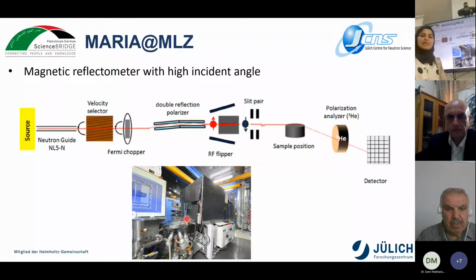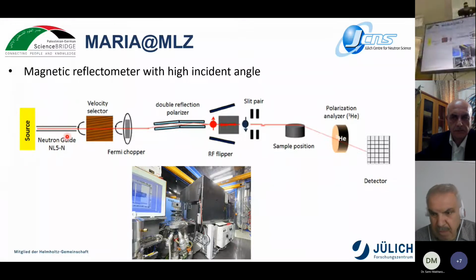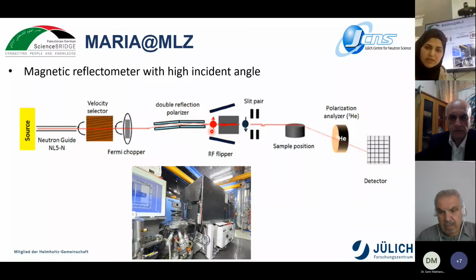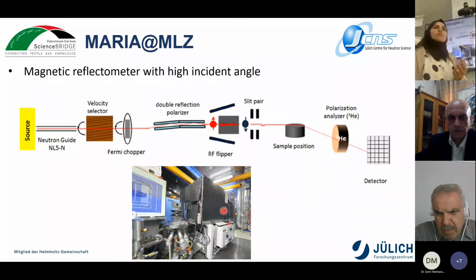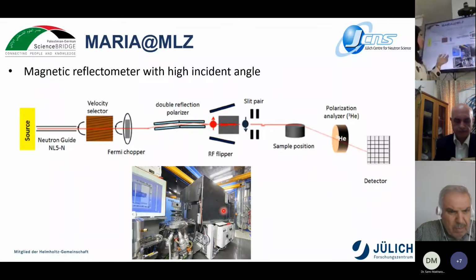Simply, for the setup, the neutrons come from the reactor and are directed toward the neutron guide, and then they go through the velocity selector and the Fermi chopper, which decides when the neutrons can start, and then we have a double reflection polarizer to polarize the neutrons. After that, they are directed toward the sample position, and then go through the analyzer, which is a helium-3 cell, and we have the detector. It's a 2D sensitive PILATUS detector. So at MARIA, we can apply a magnetic field up to 1.3 Tesla and control the temperature from 4 Kelvin up to room temperature, 300 Kelvin.